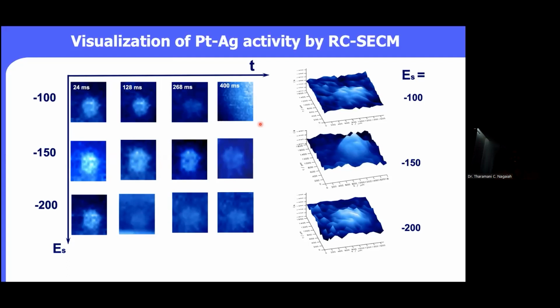If you want to apply this for industrial application, during an uncontrolled shutdown, that means when the cathode is not under potential control, this silver will precipitate on the electrode surface. It forms silver chloride, which is insoluble. And again, when the process continues, it reduces back and is available as silver with respect to the platinum. In this way, this platinum silver is stabilizing the catalyst.